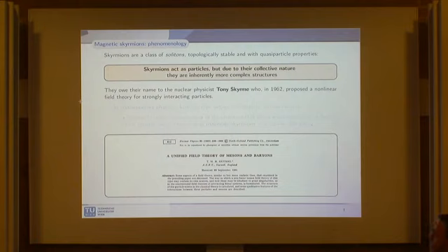And this makes them topologically stable, meaning that if the global minimizer has a lower energy level, still to pass from the magnetic skyrmion configuration to the lowest energy level requires some discontinuity in the process, according to some well-known theorem that we will see. So they are topologically stable because they minimize the energy in some homotopy class, and to pass from one homotopy class to another one, you need to put some energy into the system.